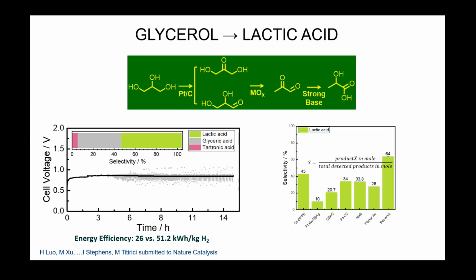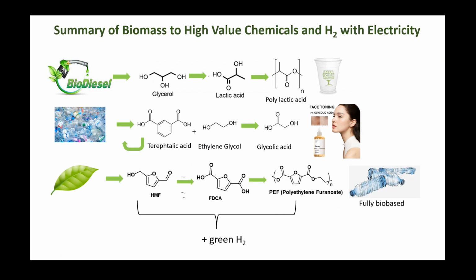So based on this, we have actually succeeded to selectively convert glycerol to lactic acid, with quite high selectivity compared to the literature, through a mixed electrochemical and chemical path, while on the other side we've happily evolved hydrogen. And because of the lower potential at which the biomass, the glycerol oxidation happens, we have a very good energy efficiency: 26 versus 51 kilowatt hours per kilogram of hydrogen. So this is with water electrolysis, and this is with our process.